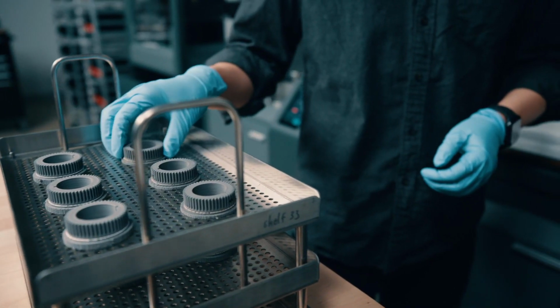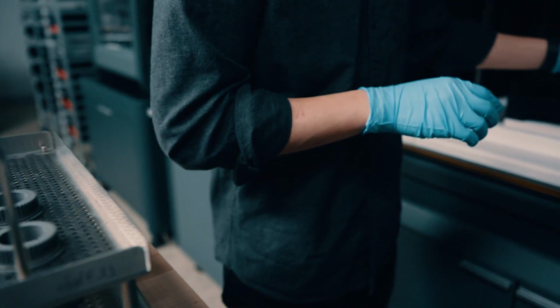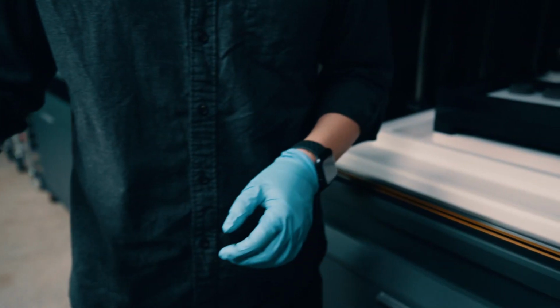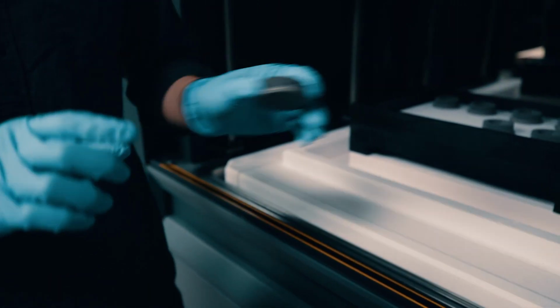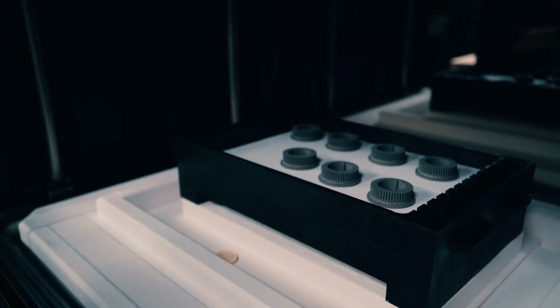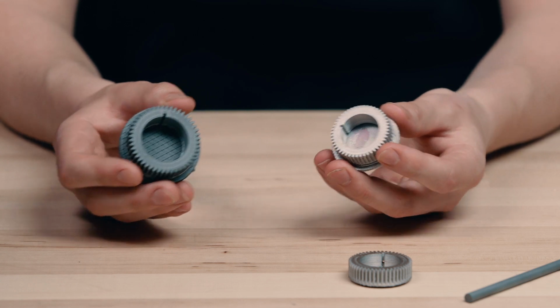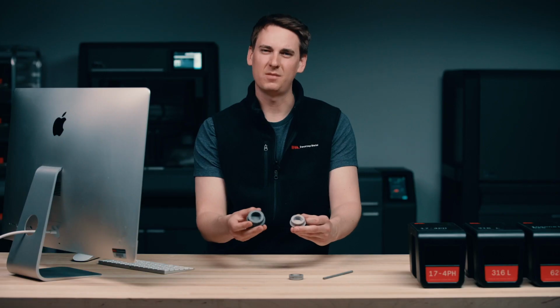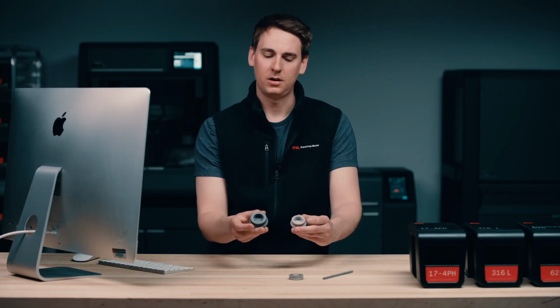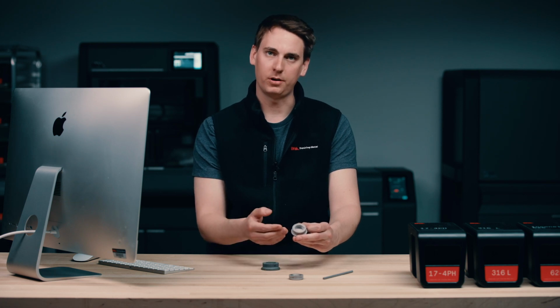With the brown part correctly positioned in the furnace, it will be heated in a sintering cycle, which is fully controlled by Fabricate. During this heating process, the remaining binder is evaporated and the metal particles fuse together. As you can see here, the part's going to shrink by about 15%. This is due to the metal densifying in the furnace. What you're going to end up with is a strong metal part.